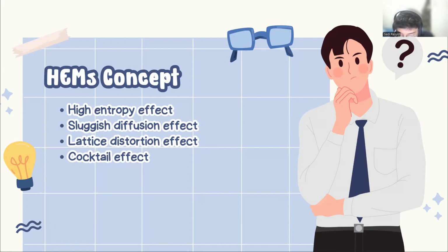The second perspective posits that multi-component structures tend to form more non-active components that are less likely to transition to vacancies compared to active components. Phase transition in high entropy materials necessitates the synergetic diffusion of multiple elements. Thus, the coexistence of active and non-active components leads to differing diffusion rates, which prevent aggregation and change the stability of the material. Consequently, the sluggish diffusion effect in high entropy structures significantly improves the durability of HEM in various reactions.